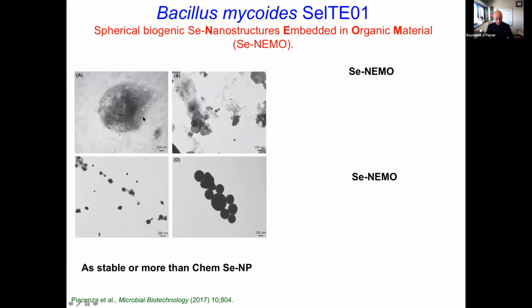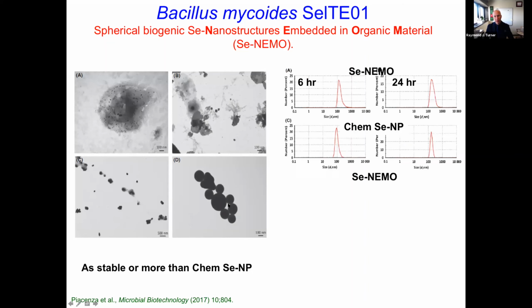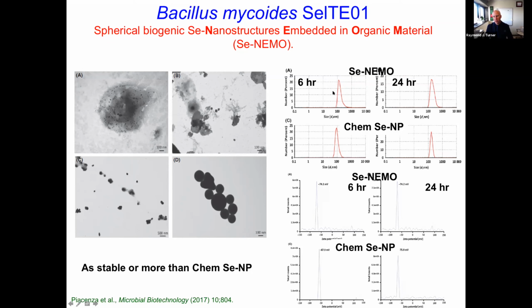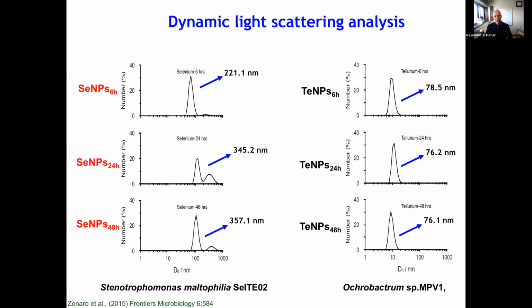Moving on, we started to play and figure out how to do things a little better. This is dynamic light scattering, giving a size distribution for the incubation time. We made chemically synthesized nanomaterial, and we could say that we had relatively the same kind of distribution, though the biogenic ones are slightly larger in size. We have a zeta potential here, which is the charge density of the material, which gives us an idea of stability. And we found this organism could make just as stable particles as we could as chemists. Here's a couple of other organisms.